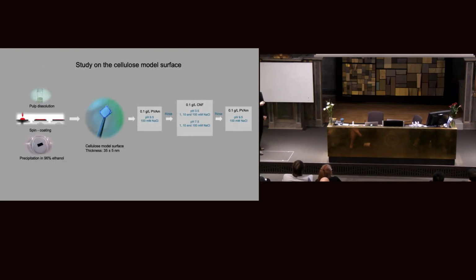To study this, it is quite impossible to study on the scale of fiber because the surface of the fiber is very heterogeneous. And if you're using fluorescent microscopy, the fiber will autofluoresce. It will hinder the signal from bacteria, and it makes it impossible to visualize. Therefore, we need a smoother and more homogeneous surface.